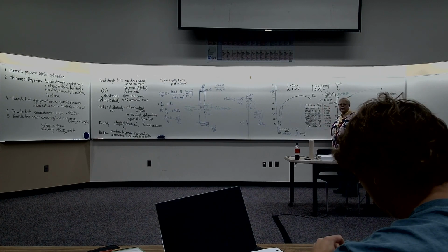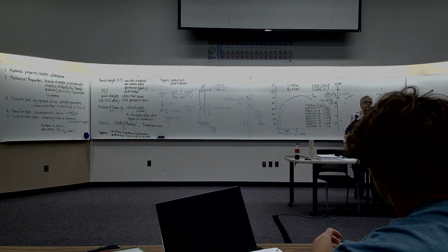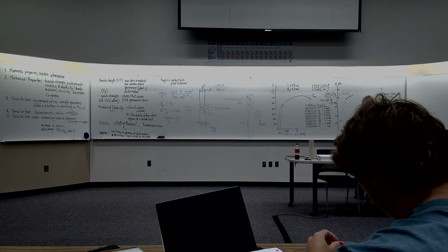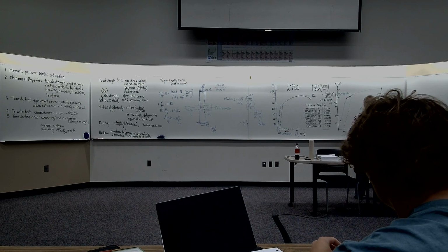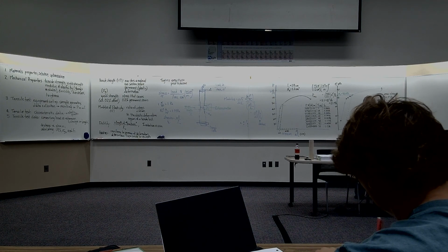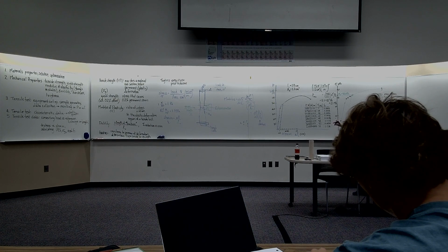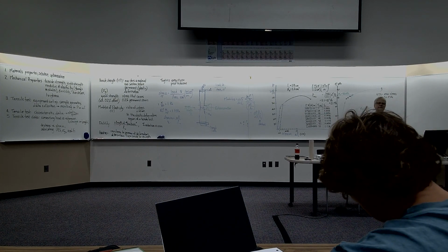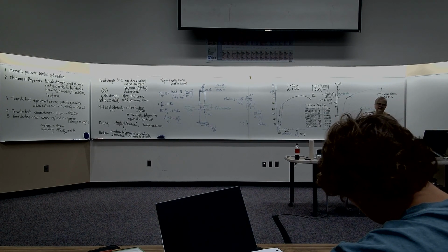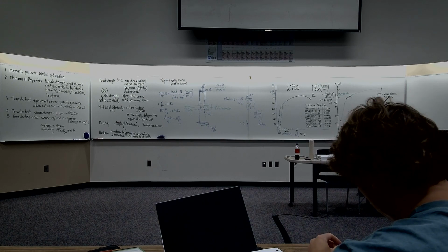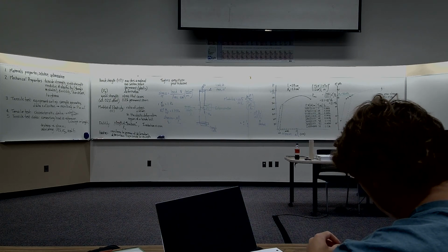So these first three are in the linear region. So I can choose any two of those three. Do not choose the 0.00. Okay? Between the 0 and the first data point, there's a lot of adjusting that sometimes happens in the setup. And so you can't use the 0.00 as a data point.